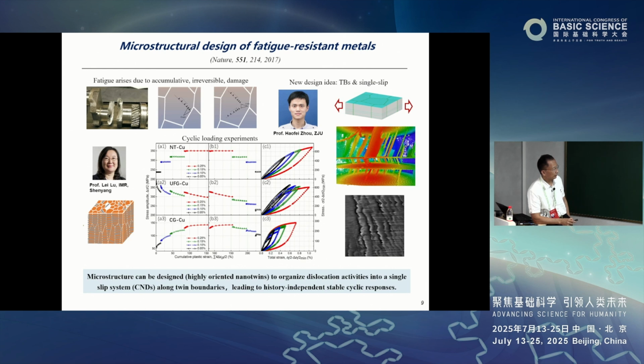You avoid both scenarios. In this case, our collaborator from the Institute of Metal Research in Shenyang, Professor Lei Lu, helped us test these ideas. She found, indeed, here are coarse-grain traditional metals and ultrafine-grain metals, and these are the nano-twin metals. She fabricated them in the laboratory and proved this nano-twin structure has very unique properties. Even with more than 20,000 cycles, there is no damage in the material. The material becomes totally reversible.